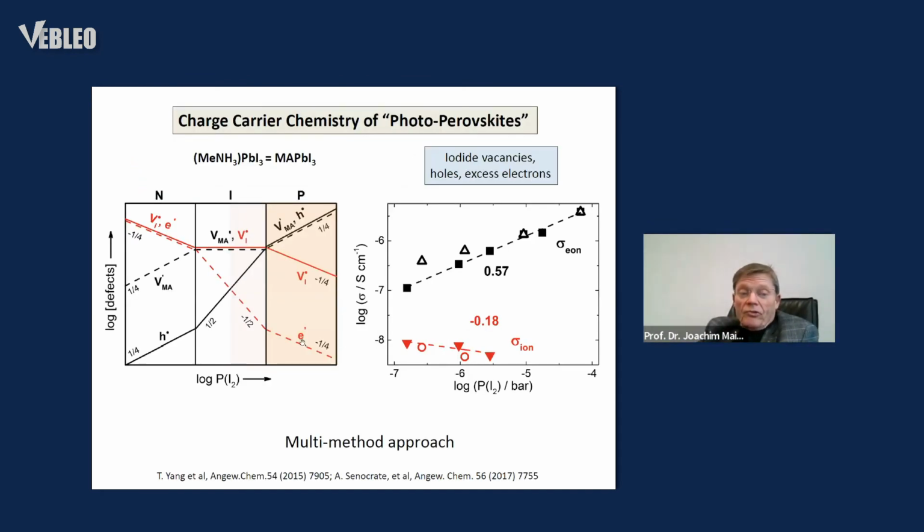And this gives rise to all these strange phenomena. Again, you have to deal with the strange diagrams that take a while to get adjusted to, but don't worry. I just want to mention they explain the situation, at least in equilibrium. So there is essentially p-type conductivity here, and there is iodine vacancy conductivity. We have shown this by many, many different experiments.